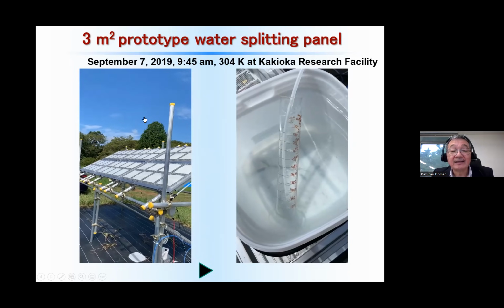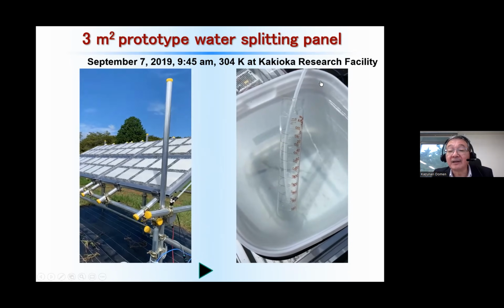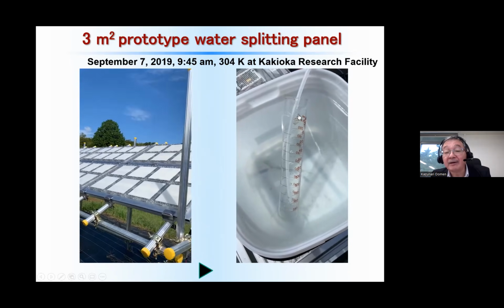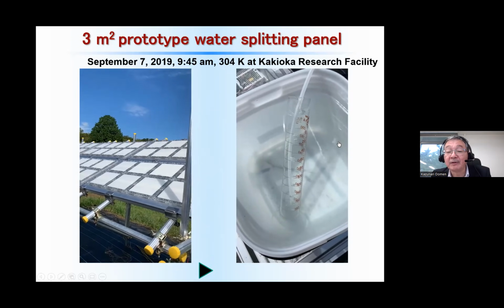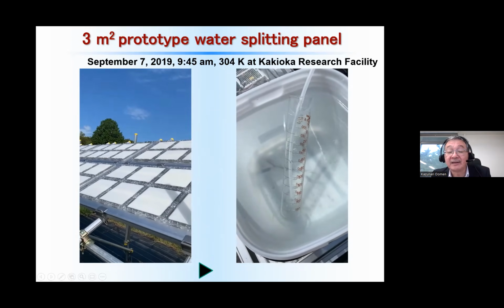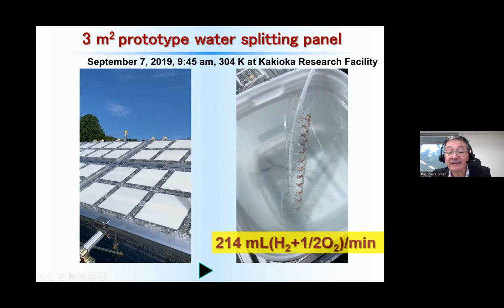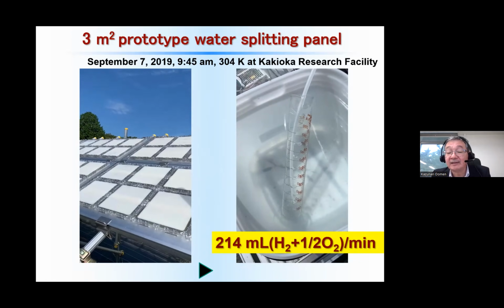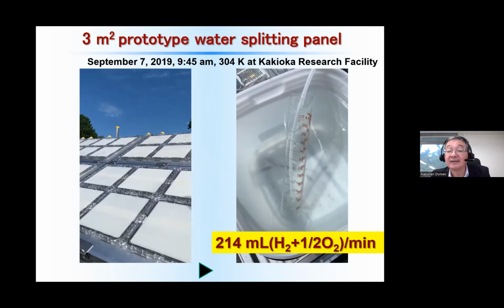Okay, this is a real one. And on the right-hand side, the bubbles are coming out. This is evolved hydrogen and oxygen from this 3 square meter system. And in this case, about 200 milliliters per minute of hydrogen and oxygen is evolving.